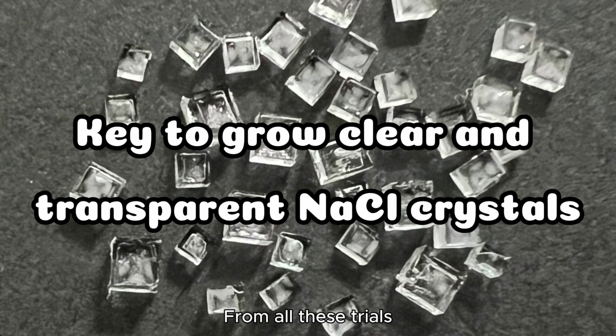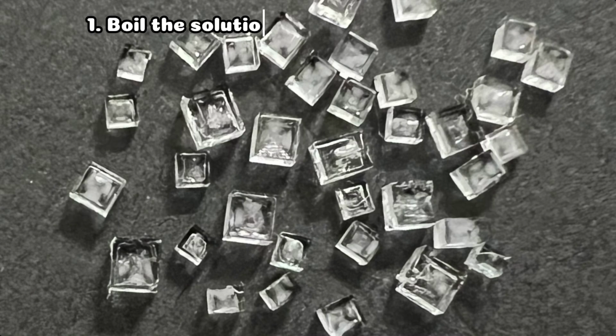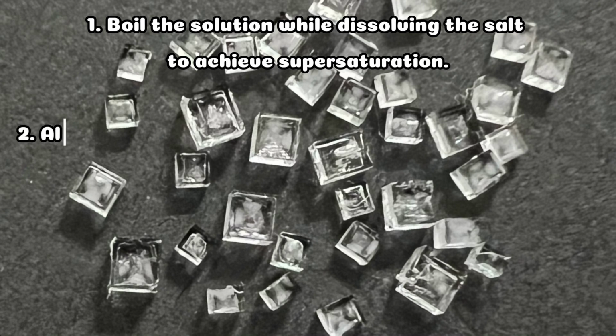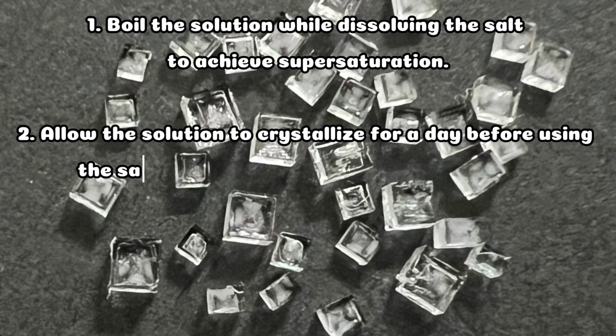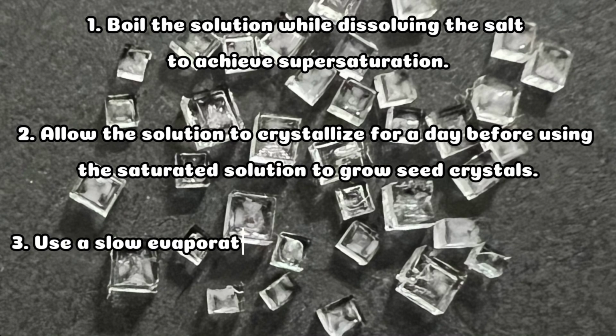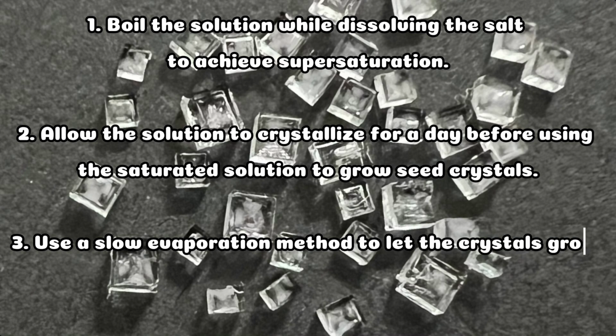From all these trials, I learned that the best way to grow clear and transparent NaCl crystals is to boil the solution while dissolving the salt to achieve supersaturation, allow the solution to crystallize for a day before using the saturated solution to grow seed crystals. Lastly, use a slow evaporation method to let the crystals grow larger and maintain their clarity.